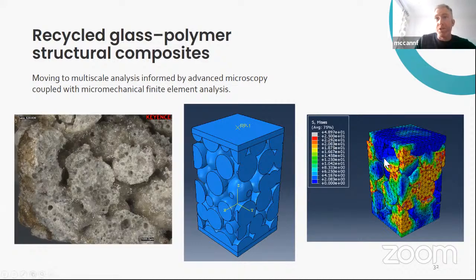Now, just to give an indication on the legend here, the red stresses here are 25 MPa. So we can see locally the glass, and that's around the crushing strength of glass, is around 20 to 25 MPa. But if we then get an effective strength across the entire cross section, so that's incorporating the polymer, the glass, and importantly the air voids, we actually end up with a very similar result of around 2 to 2.5 MPa for, if you want to call it, the merged material.